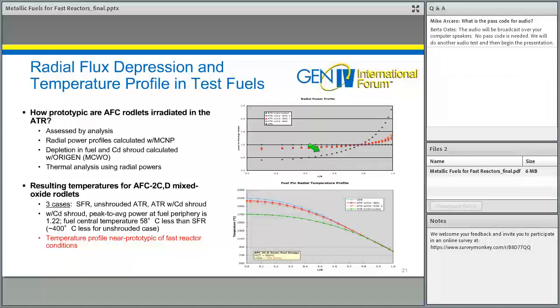But what we've been able to achieve with the cadmium shrouding is a change that looks like these yellow and red curves here. So it still does have some peaking at the periphery. It still has some depression in the fuel center, but these have been dramatically reduced. And when you translate this power profile into a temperature profile in the test pins, what you see is a profile that is very close to what you would expect in a genuine fast reactor. It's certainly not the dramatically altered profile that you would have in a thermal spectrum.